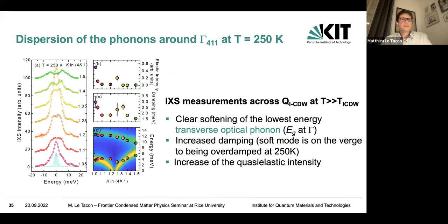Just to say a few words about the phonon. We did this measurement with the resolution that gives us the largest flux, at 3 meV, and that's the phonon spectra, how it looks. So we nicely see some well-defined phonons here. We can fit this. The solid line below is really the fit to the data.